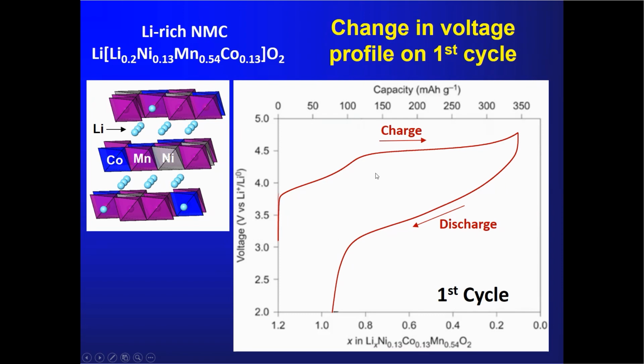So what you see on the right is a typical load curve, a typical voltage versus capacity or composition curve as one charges a cell with one of these materials as the cathode and then subsequently discharges it. And you see with the shading that the initial charging process is largely associated with transition metal redox. So one extracts lithium as one charges, and that is charge balanced by the oxidation of the transition metal ions, in this case mainly nickel, but also cobalt. And if you stop here and then come back again on discharge, you will follow pretty much the same curve.